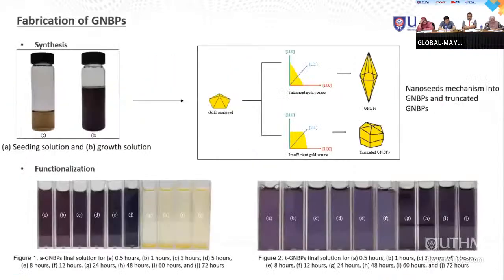This is the result solution after we synthesize and functionalize GNBPS. For the synthesis, there is a mechanism of growth from seed, and increasing time leads to the decrease of gold source, which affects the production of truncated GNBPS, so they cannot grow in perfect shape. Figure 1 shows the AGNBPS or amine functionalized GNBPS final solution from 0.5 hours until 72 hours.